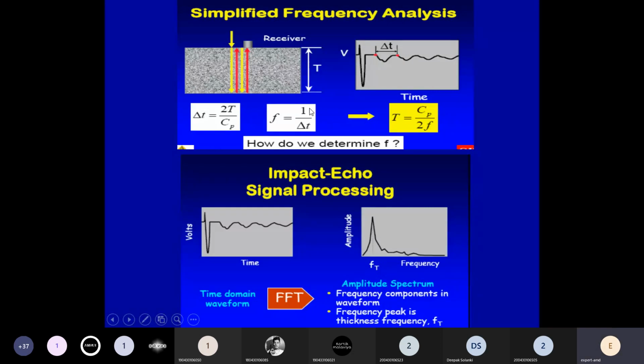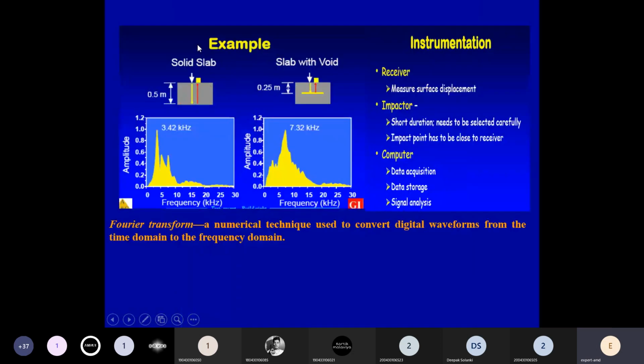And it also gives a frequency. So frequency is basically 1 upon T. By using the Fourier transform, you can easily calculate amplitude versus frequency. If you need to understand in terms of an example, see, if your slab is solid, for example, and the depth of the slab is 0.5 meter, we will give an impact and it will come back. So if it is of complete thickness, your amplitude versus frequency is this. Your frequency is in the range of 3.42 kilohertz.